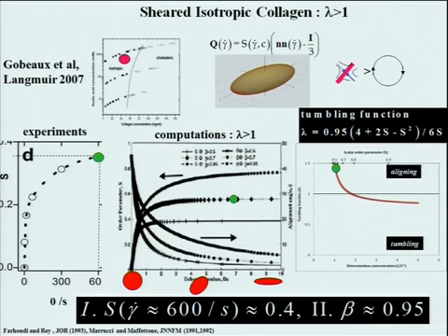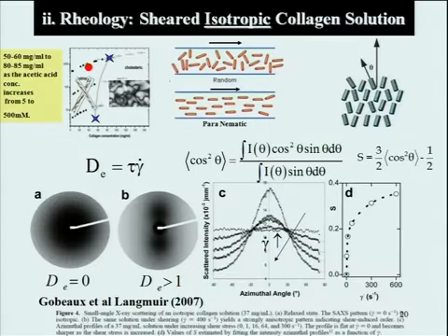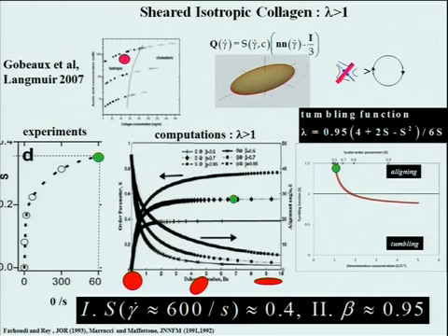From this curve, matching two experiments, as indicated here, and using our theory, now we have a tumbling parameter as a function of concentration, and find that we start here, the root is here, therefore the reactive parameter is greater than 1, and these things don't tumble in shear, they flow aligned.